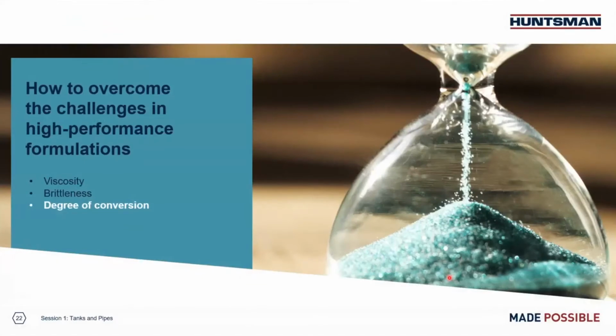Using reactive liquid polymers allows us to improve adhesion and reduce brittleness, all without losing chemical resistance. At dosage levels of around 10% on formulation, as Yong just mentioned, the impact on the glass transition temperature is also minimal. So let's look at the effect of curing and glass transition temperature on chemical and temperature resistance of coatings in the following part of the presentation.